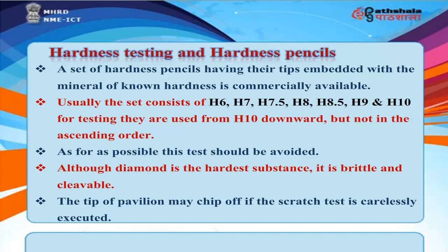Hardness testing and hardness pencils. A set of hardness pencils having their tips embedded with a mineral of known hardness is commercially available. Usually, the set consists of H6, H7, H7.5, H8, H8.5, H9, and H10. For testing, they are used from H10 downward, but not in ascending order. As far as possible, this test should be avoided.